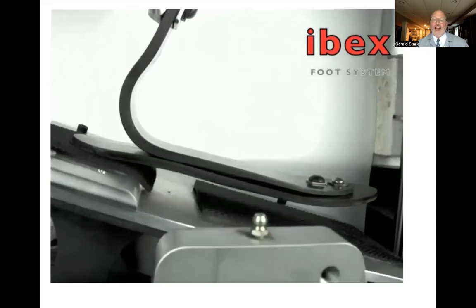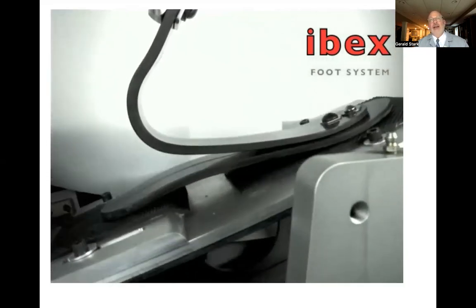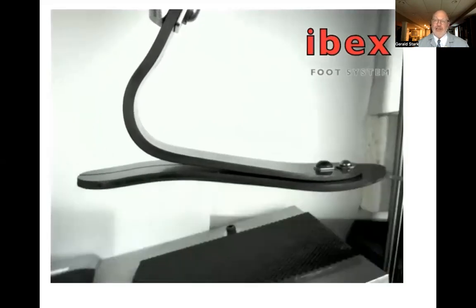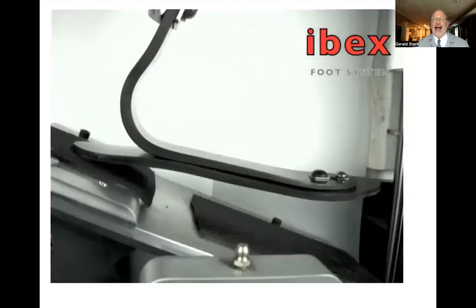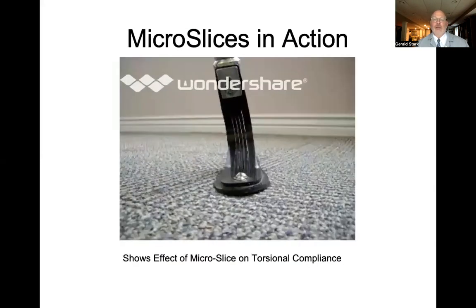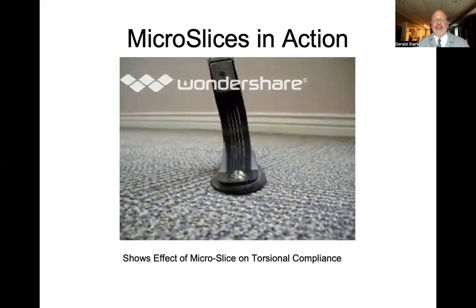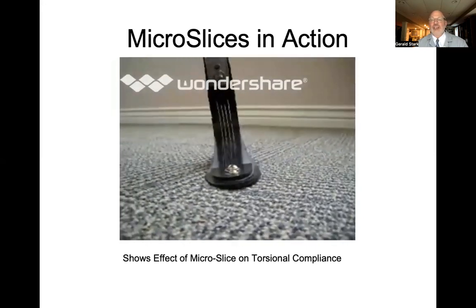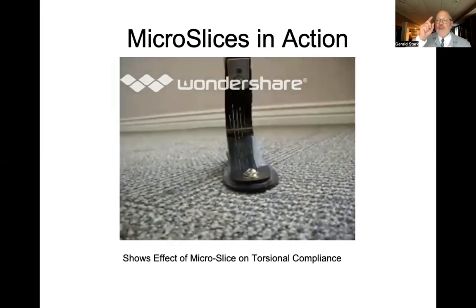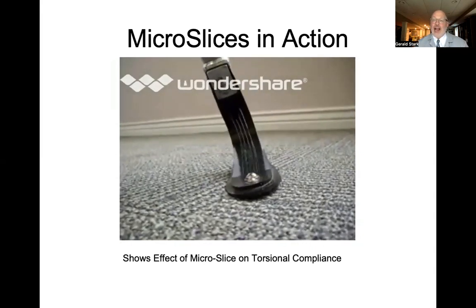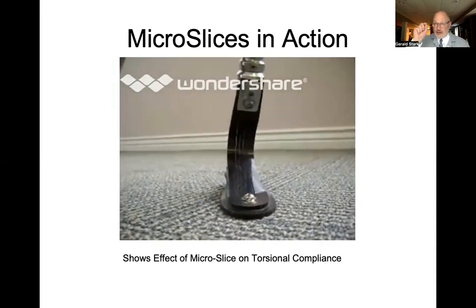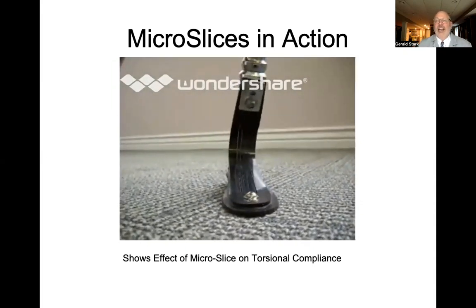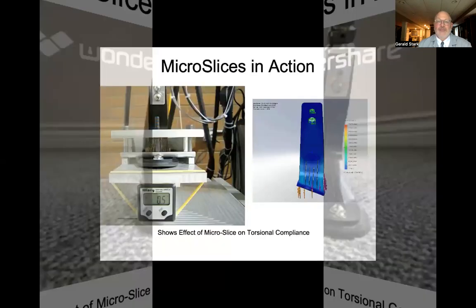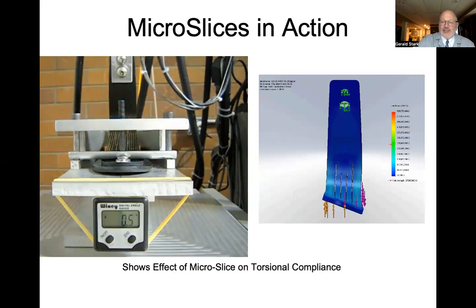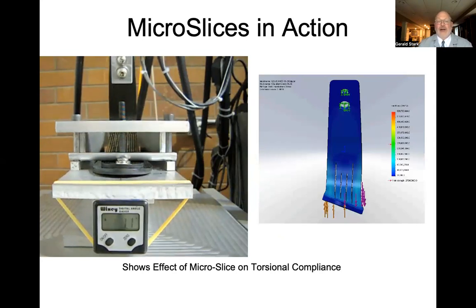And when we think about orthotics too, it's flexing quite a bit. So it's not a matter of what we're locking out, it's what shape, what types of motions we're allowing. So when we look at things like making small cuts, we can see that this changes some of the inversion and eversion because we're removing some of those fibers. And you can imagine what happens if not all of those fibers are adhered to, or if over time there are small cracks that change the flexibility of that material. And here you can see what happens when we apply a certain amount of load, the stress versus strain.